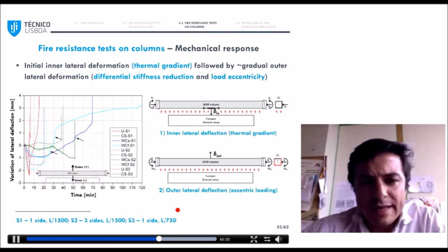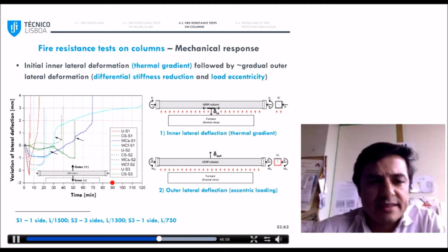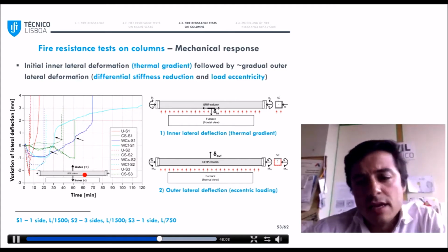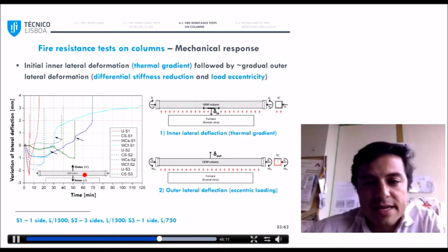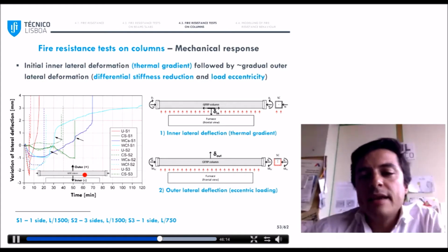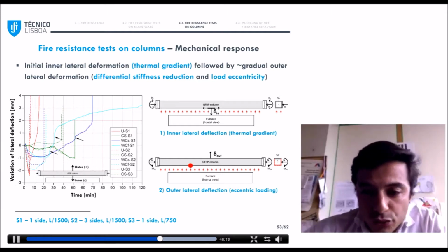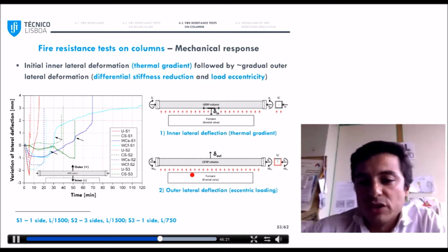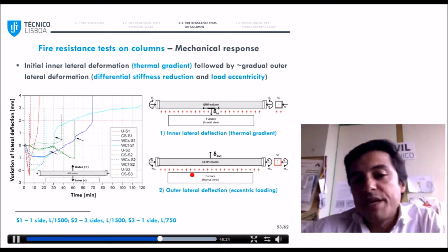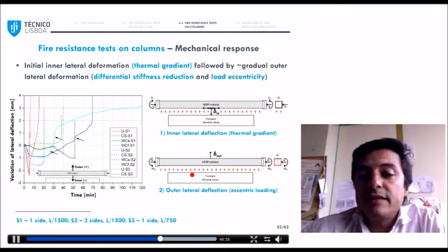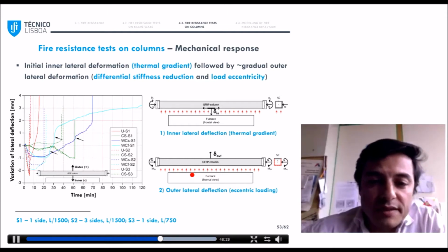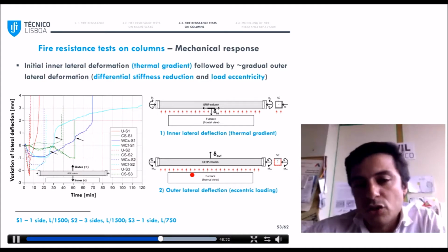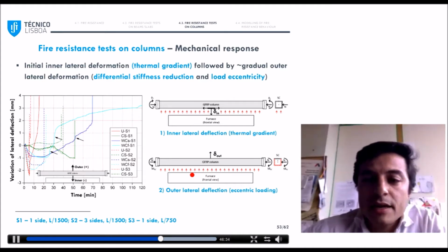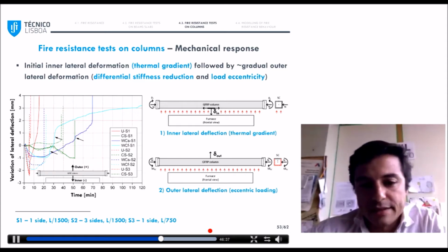In terms of lateral deflections, so out-of-plane deflections, the columns first presented inner lateral deformations. This was basically due to the thermal gradient installed in the section, and then they progressively presented outer lateral deformations due to two reasons. First, the differential stiffness reduction, which was much bigger in the bottom part of the section, and also due to the eccentricity of the applied load, whose position was kept constant during the test with respect to the stiffness center of the section.